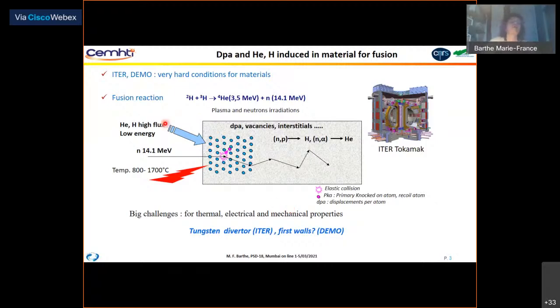Of course, high flux of hydrogen and helium, and also high heat fluxes with temperatures that could reach 700 degrees C, and also neutron irradiation. This irradiation could lead to elastic collisions producing PKAs, that means primary knock-on atoms or recoil atoms, and it leads to the formation of displacements, so vacancies, interstitials, and there are also some nuclear reactions which are created in the material. So of course, this irradiation will change the chemical composition and also the microstructure of the material.